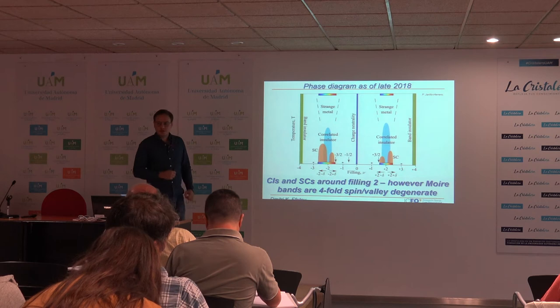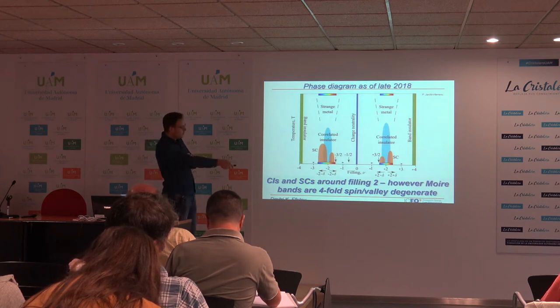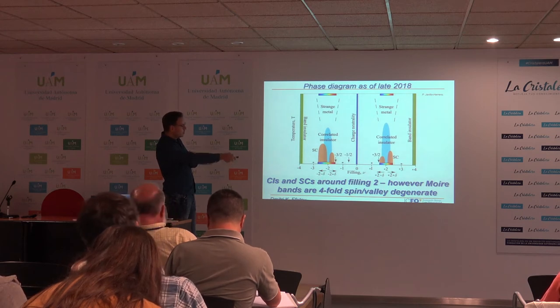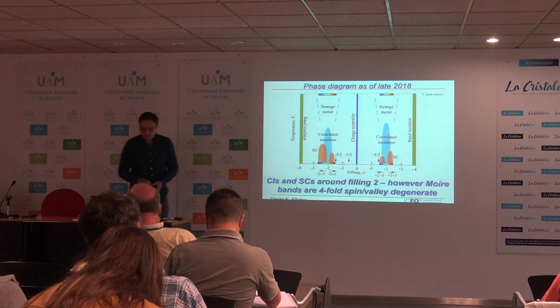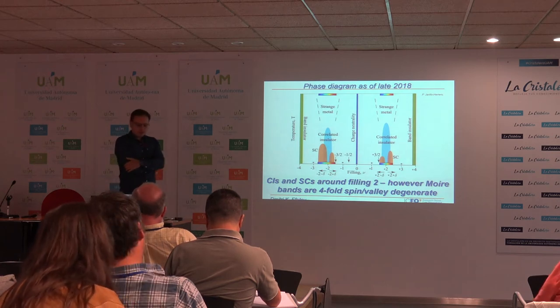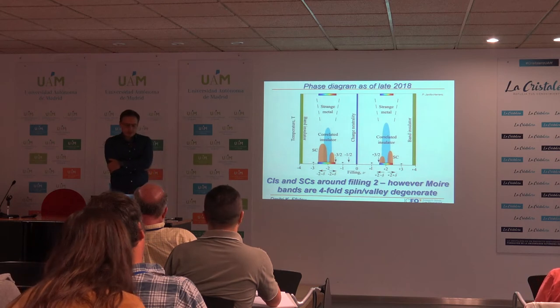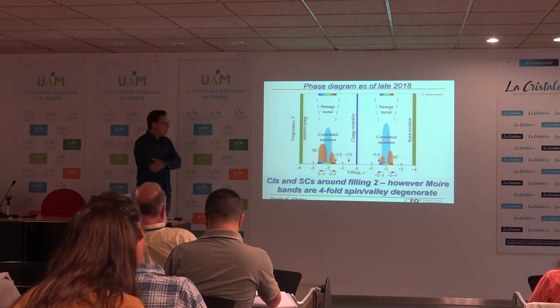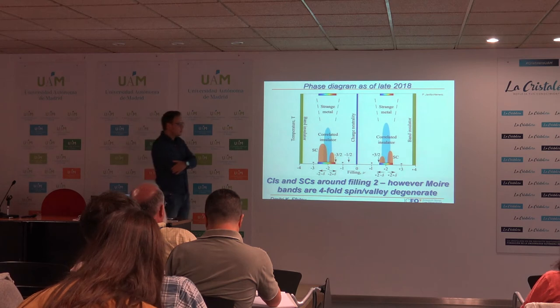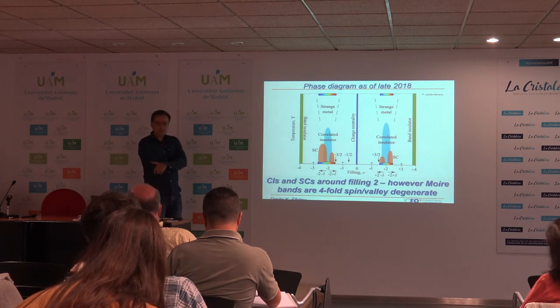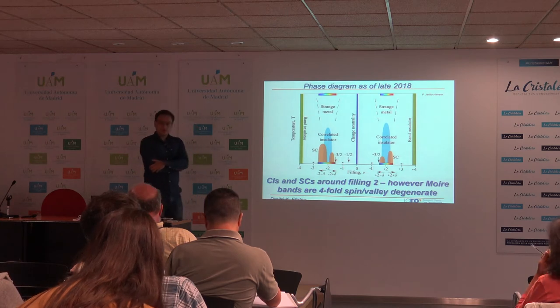And in the middle of each of these bands, at exactly half filling, or in other words, minus 2 electrons and plus 2 electrons, this is where the correlated insulators appear. And this is where also the superconductors appear. Okay, but I think immediately when we started looking at this, the question arises: why do these correlated insulating states, the superconductors, appear only at minus 2 and plus 2 electrons?